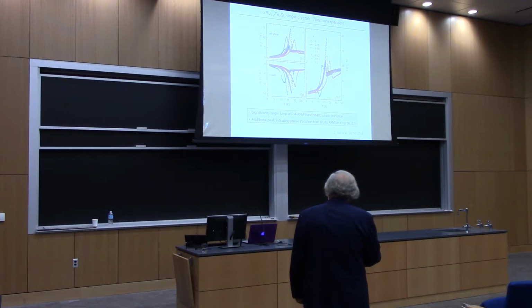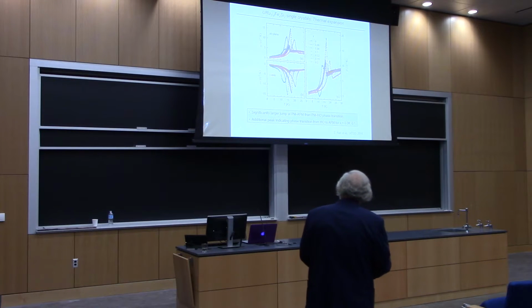And you see significantly larger jumps at the paramagnetic and antiferromagnetic transition than at the paramagnetic and hidden order phase transition. That's one thing to notice. And then you see some additional peaks when your concentration is like 0.08 and 0.1, which is close to the boundary, you actually see two peaks. And these we believe are associated with the transition from the paramagnetic phase to the hidden order phase as you lower the temperature, and then from the hidden order phase to the antiferromagnetic phase.